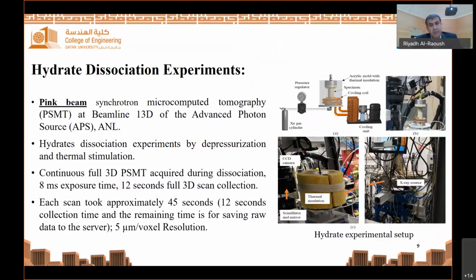This is the experimental setup that we used for hydrate formation and dissociation experiments. The setup was designed to control the pressure and temperature to simulate the formation and release of hydrate from deep reservoirs. Pink beam synchrotron tomography was used to obtain non-destructive 3D images. Pink beam uses a grazing incidence mirror and an X-ray absorbing foil instead of the monochromator to eliminate high and low energy photons, which gives a high flux of X-ray 3 orders of magnitude higher than the monochromatic beam.